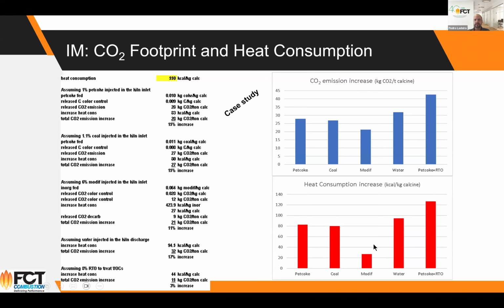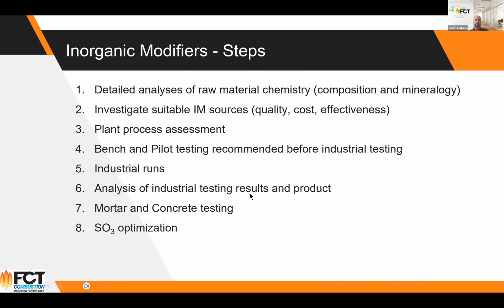The same trend goes for the heat consumption. The one with the lower increase in heat consumption is proven to be the inorganic modifiers. So in the end, although you're using calcium carbonate as a means to control color, and you are emitting CO2 out of the calcium carbonate, the overall heat consumption and the CO2 emission increase is less than the other methods. So that's one important feature of this inorganic modifier solution.